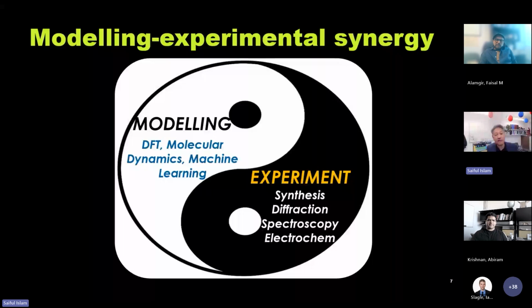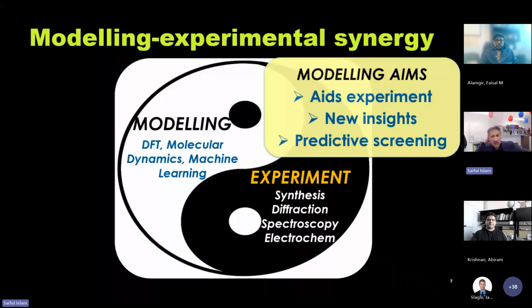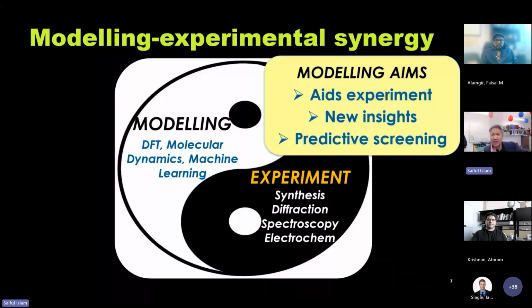So on the modeling side, we use density functional theory, molecular dynamics, but increasingly we're coupling the two using machine learning interatomic potentials. On the experimental side, people use synthesis, diffraction, spectroscopy, and electrochemistry, and a range of other experimental techniques like microscopy as well. But there's a strong synergy in my group between the two. For the non-modelers, let me remind you about the key modeling aims. Three main aims, I think, of modeling. One is, can we help to aid and interpret experimental data? The second aim is, can we get new insights that experiment might have difficulty with, perhaps on the atomic and electronic scale? And then lastly, can we use modeling as a predictive screening technique? Probably the most challenging part of modeling.